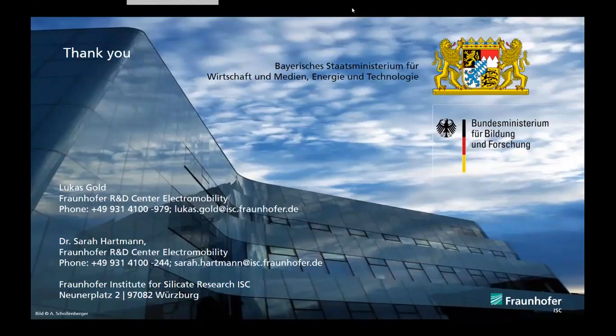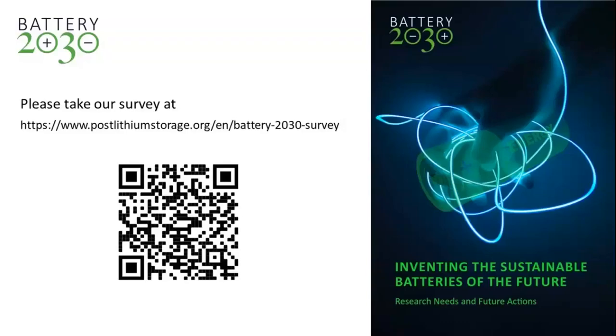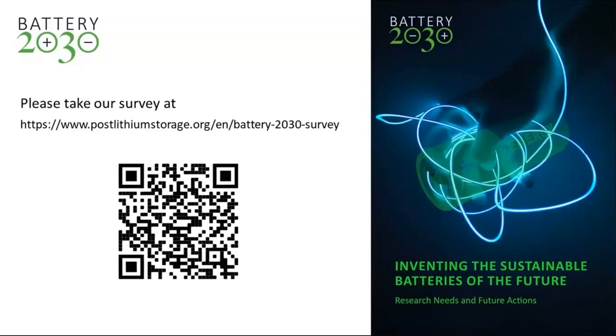The beauty of Battery 2030 Plus to be chemistry neutral is that you can test new techniques on well-known systems. And Valerio Conta is asking, can you test this also on NMC? Have you tested it, and are there any important differences? Yes, so it's important to have a change of mechanical properties related to state of charge or aging conditions, and especially high effect you have on the graphite anode, and it's not so dependent on the cathode actually, but we also of course did measurements with NMC, and we see the same behavior as well.